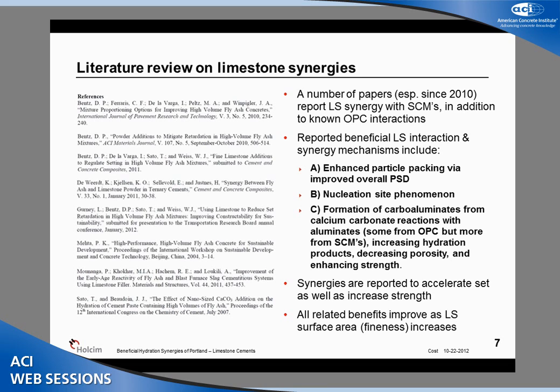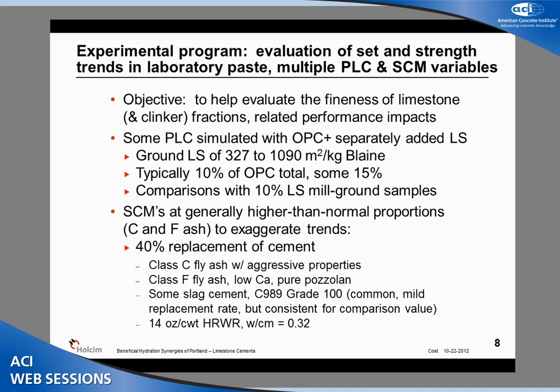It's actually the formation of new hydration products, carboaluminates, that result from the interaction of calcium carbonate and aluminates in the system. And this is particularly interesting from a number of viewpoints as you begin to look at systems with SCMs involved, because some of those systems contribute additional aluminates that can combine with the calcium carbonate. And testimony to that is that many of these authors have reported that these synergies and the strength and setting time trends began to improve further as we further increase the available surface area of the limestone.